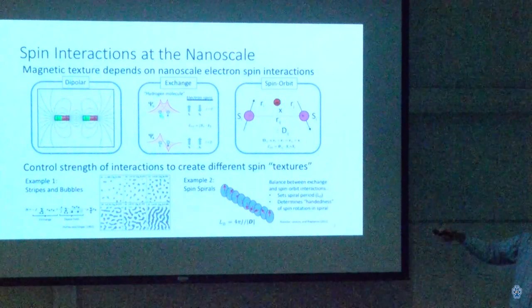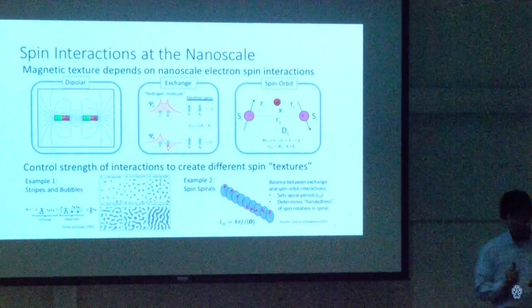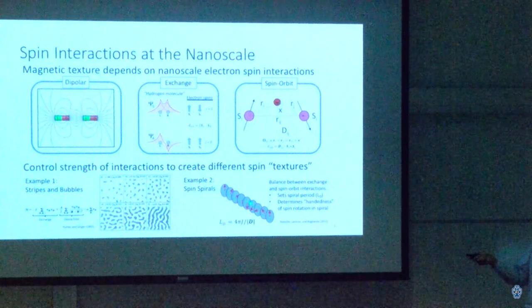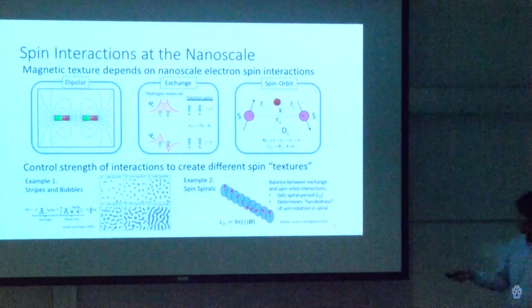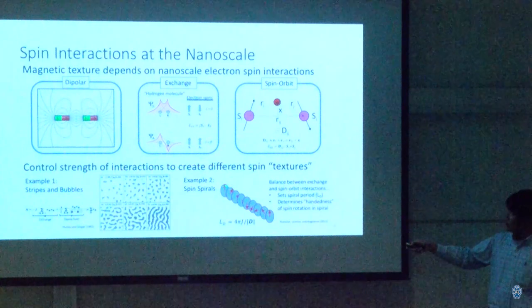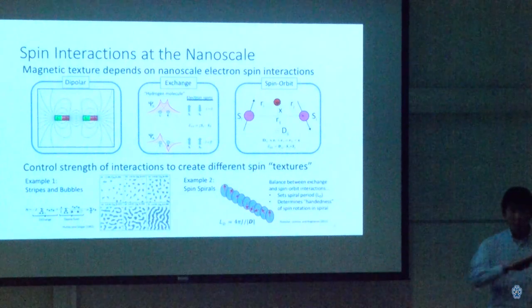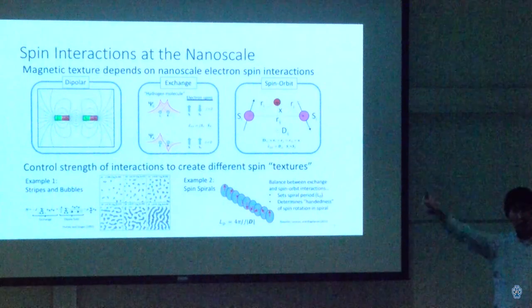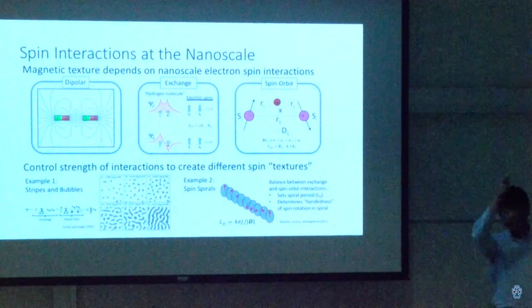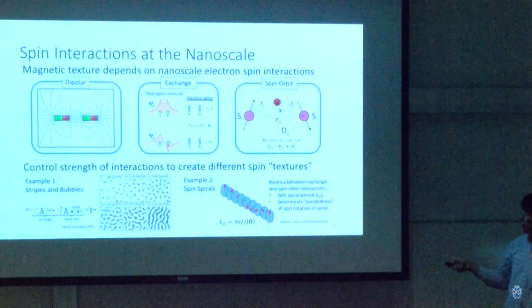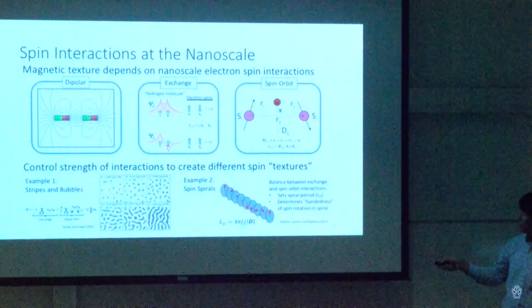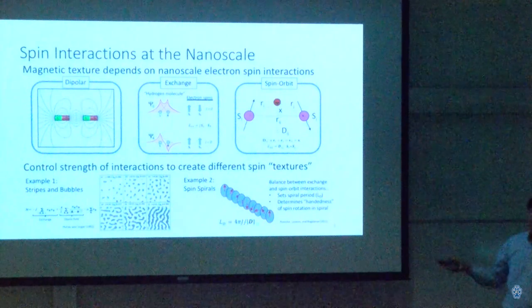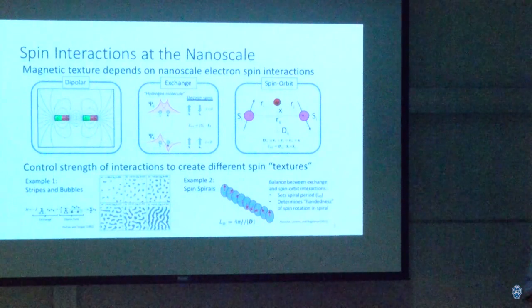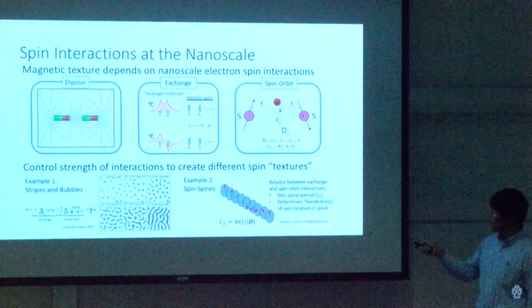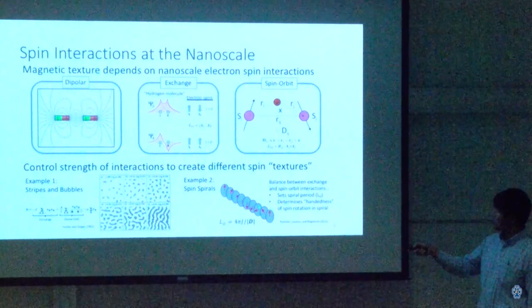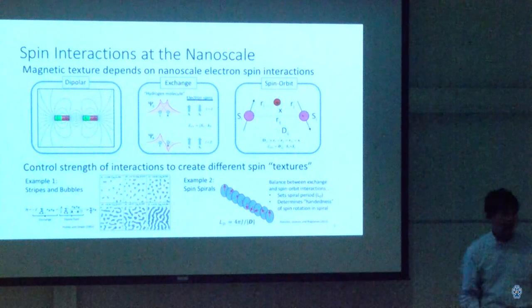On the other hand, if you change the relative strengths of exchange and spin orbit interactions, you can get something called a spin spiral. And you'll see an example of that in a moment. The spin spiral, in this case, causes the electron spin from one atomic plane to another to slowly rotate until it fully executes a turn. And the period of that is expressed as the ratio between the spin exchange constant and the magnitude of this spin orbit vector D. The sign of D also affects how the spin spiral spins, whether it goes clockwise or counterclockwise.